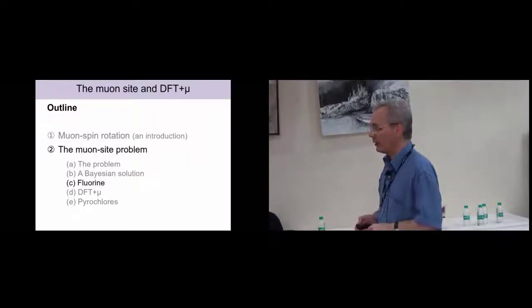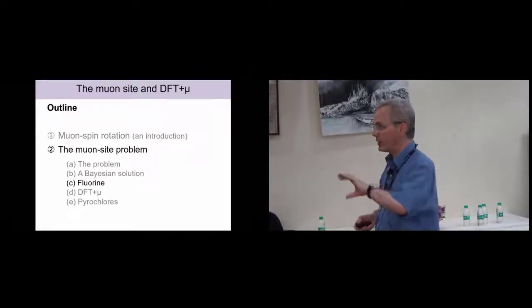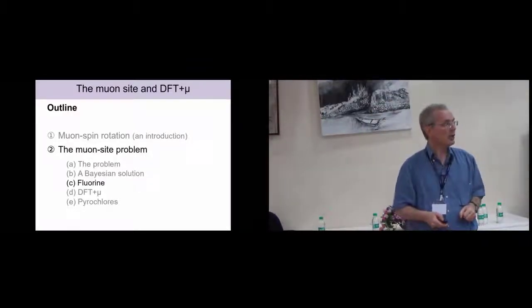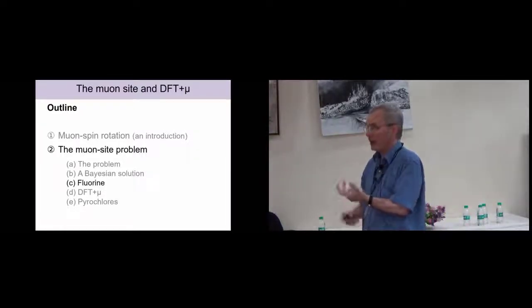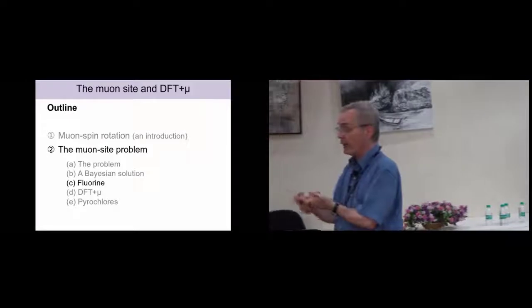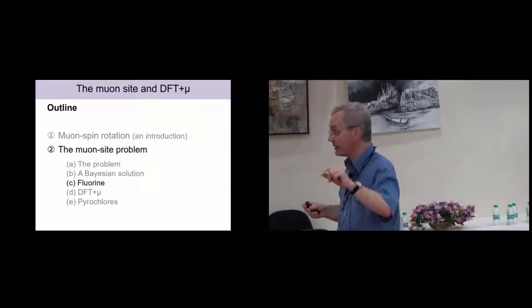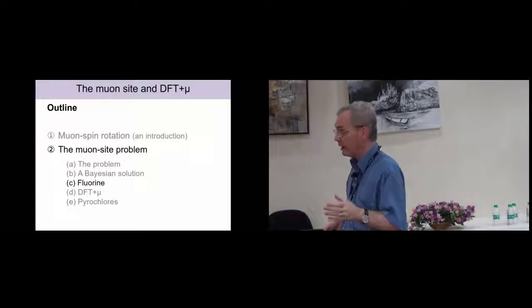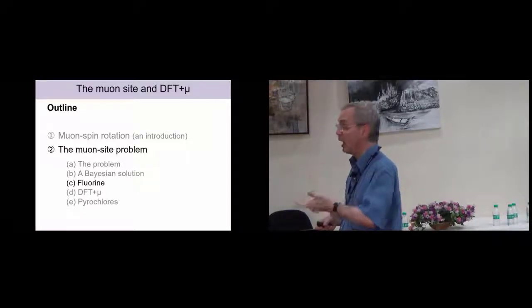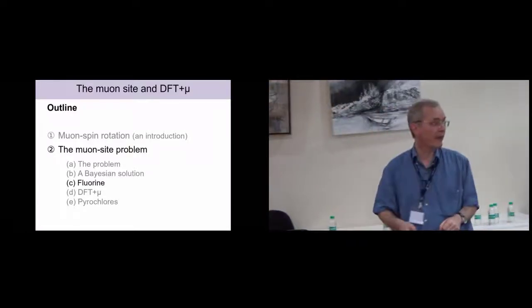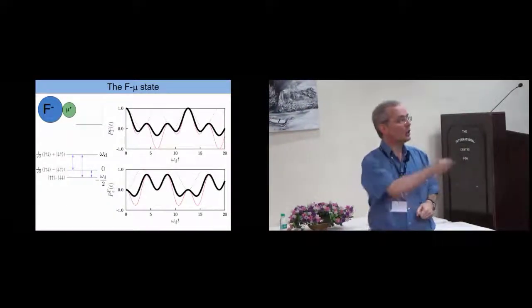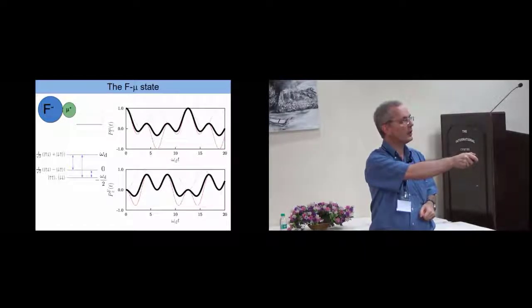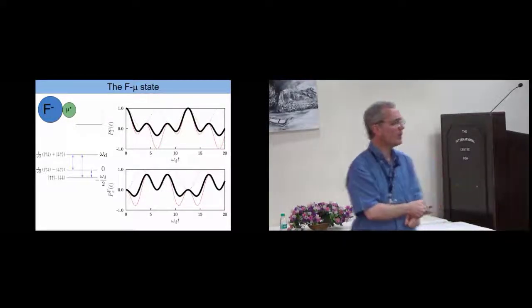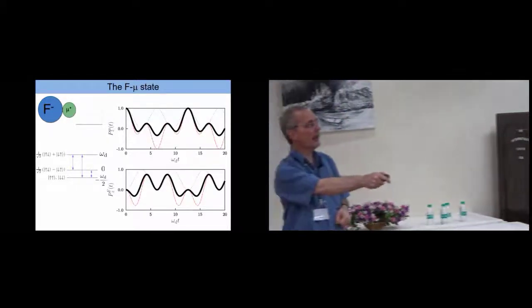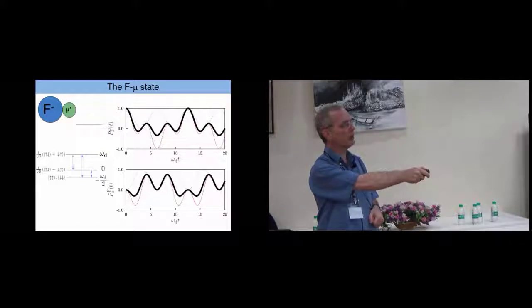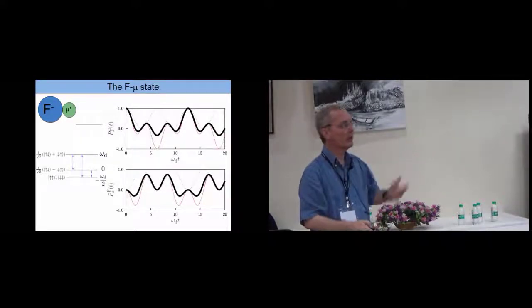Let me tell you about another solution, or as a second possibility, and that's the use of fluorine. So it turns out that muons love fluorine. They love fluorine because fluorine in many compounds is there as F minus. This is the most electronegative ion. So mu plus, being essentially a light proton, really will go for the F minus ion. And when it does that, you have a beautiful dipolar interaction between the muon and a nearby fluorine. So what happens in this particular case is that you get a resonant transfer of polarization between the muon and the fluorine. If you just solve the dipole Hamiltonian for